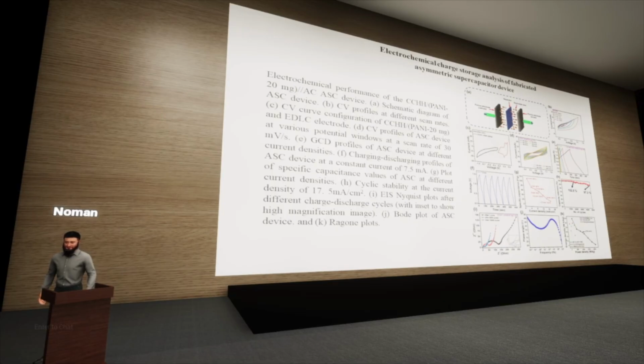Then by choosing this material as a positive electrode and activated porous carbon as a negative electrode, we made an asymmetric supercapacitor device. This is the schematic representation of this supercapacitor device. Then we performed the two electrode assembly in which we first optimize the potential window of the device.